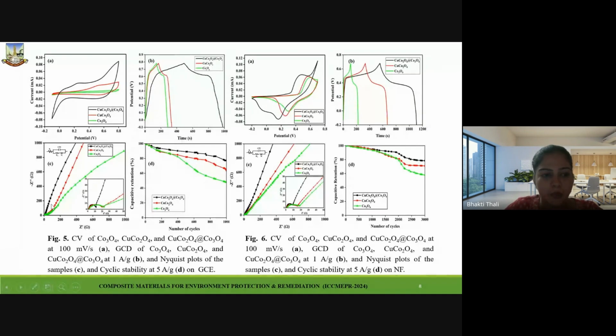Further, we have done the Nyquist plot, that is real impedance plotted versus imaginary impedance. Here also we can see that the diameter of the semicircle for the composite was smaller in both cases compared to the other materials, and the slope of the composite was larger compared to the other materials. For the stability, stability on glassy carbon was up to 1000 cycles, whereas on nickel foam it was 3000 cycles. And the composite delivered 76% on glassy carbon and 78% on nickel foam.